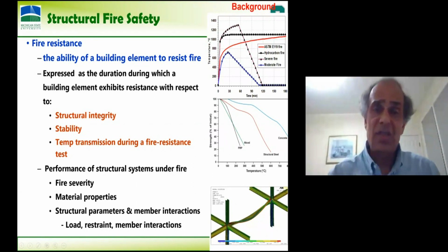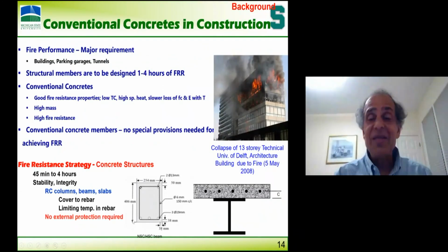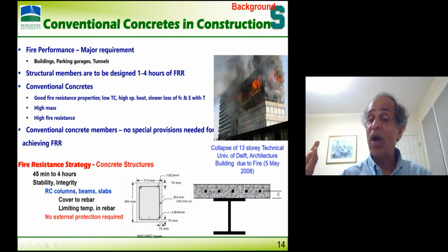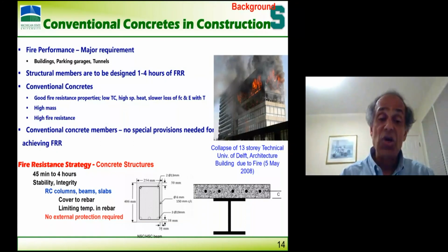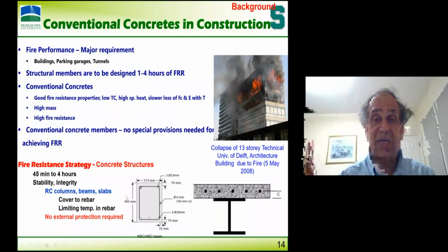Now, current provisions, if you take conventional concretes, are really very prescriptive. As I said, much of this was developed based on 60s and 70s concrete types and technologies. And as you can see, all you need to do is provide a certain cover thickness to the rebars, because steel is the weaker part in this slab, or in this one as well. As long as you have sufficient cover thickness to the rebar, you have achieved a certain fire rating. More fire resistance is typically obtained with a higher cover thickness.